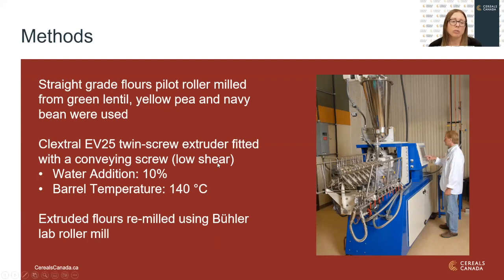This would also reduce the amount of starch damage that occurs, which we wanted to make sure that we didn't have 20% starch damage again, as we saw with the micronized samples, that just wasn't working well. After we extruded them, we remilled them using the Buhler lab roller mill. This was done just because there was some clumping that occurred, so we needed to make sure that the particle size was more consistent.